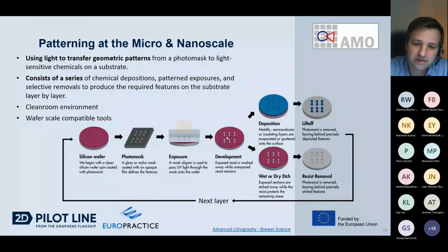Through these structures, you can then deposit certain different materials on top of this wafer. And after the lift off, you have these structures with a certain material, or you use these structures for etching. This would be the way, for example, if you want to structure graphene in a certain way. So you etch away the graphene at the positions you don't want to have it. And of course, you don't apply this patterning just to graphene, but also to the contacts and everything else you need on your chip in order to fabricate the functional devices. And this you have to repeat layer by layer.